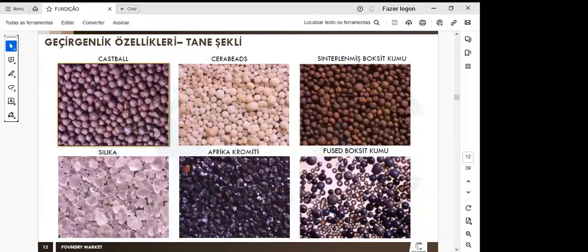Here we can see the grain shapes of the different foundry sands: Castball, Cerabeads, sinterized bauxite, alternative, silica, chromite, and a fused bauxite sand. Silica and chromite sand have an angular shape, and silica presents a sub-rounded shape. The others, ceramic sands such as Castball, mullite, and bauxite sands, normally present rounded grains.